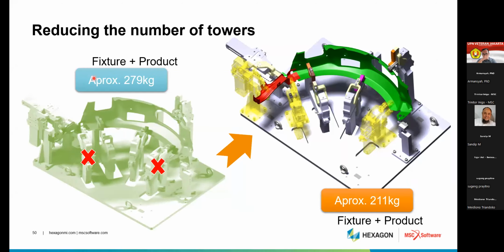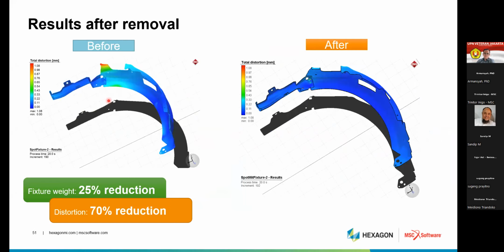After seeing that, we removed 2 clamp towers from the fixture setting and adjusted the position of the clamps. The total weight was around 279 kgs, and after removing those clamp towers, it comes to around 211 kgs. Before removing those clamp towers, high distortion was happening in this zone, and after removing them, we can see there is less distortion. So fixture weight got reduced by 25% and distortion by 70%.